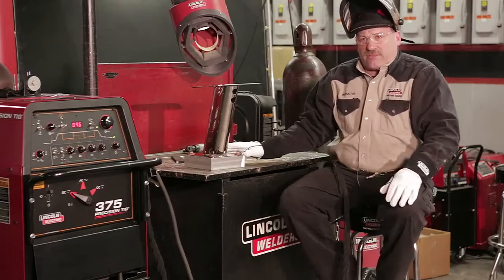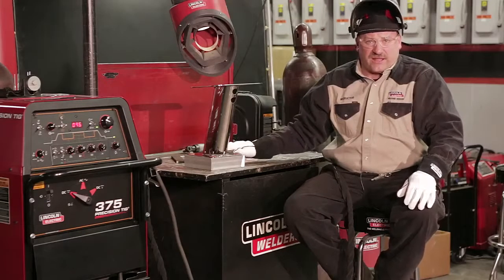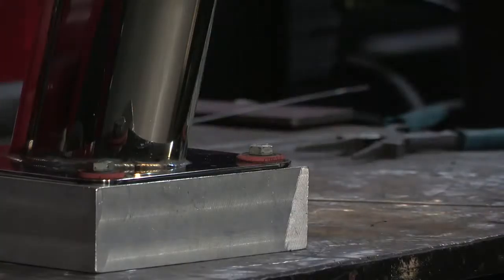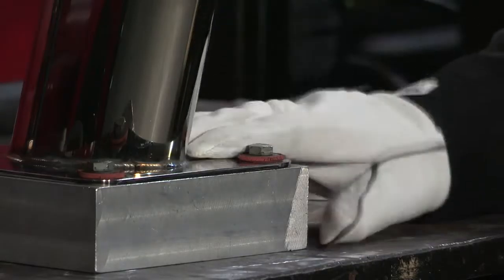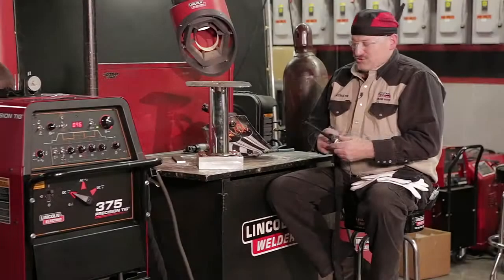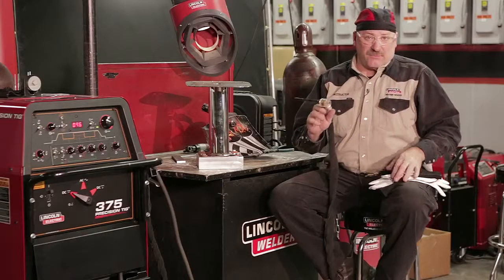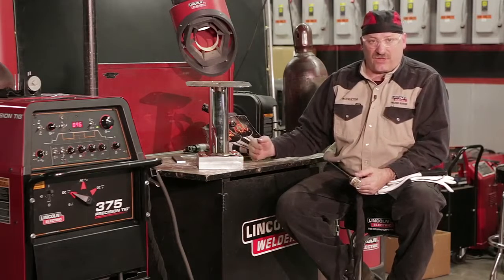What's nice about that big, thick aluminum block is it pulls the heat out of that stainless real quick. Heat transfers into that aluminum quick. Stainless doesn't move it very well. So my goal here was to keep the heat input down. And using the heat sink, that helped a lot.